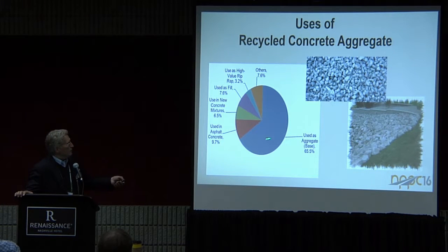Obviously, far and away the biggest use is back into base layers, taking the material, crushing it down, and using it as an aggregate base. Far and away the most common thing that's used, because it's relatively insensitive. We can use this material back in a base really without worrying too much about some of those other contaminants like the brick and the gypsum and the mortar and even asphalt materials and things like that that might also be included in the concrete at the time of recycling.